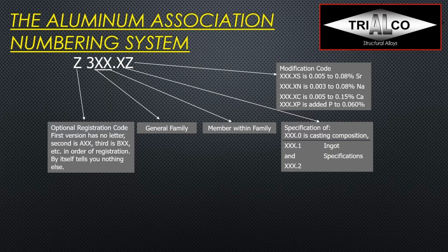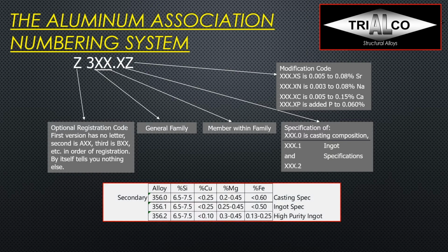And then we will sometimes find a letter behind these numbers with a dot 0 or 1 or 2. And those letters mean, okay, so if I have an S behind it, then it's strontium modified. If it's N, then it's sodium modified, C with calcium, and P with phosphorus. So pretty simple. If we have a look at one example, I mentioned already before, 356, we have the dot 0,